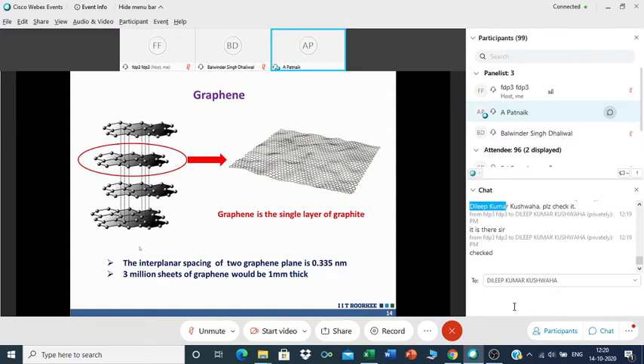On the left hand side, you see graphite. It's multi-layer; a number of layers of graphene will make graphite, as I told you in the very first slide. So a single layer of that is a graphene sheet. Graphene is the single layer of graphite. 3 million sheets of graphene would be 1 millimeter thick. So from this, you can find out the thickness of this particular graphene material. The interplanar spacing of two graphene planes in this graphite layer is 0.335 nanometer.